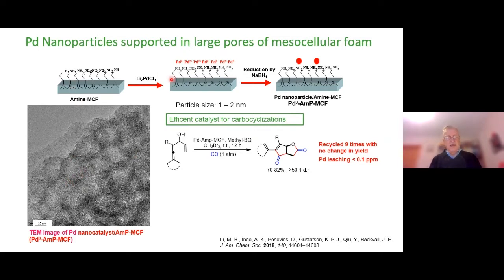And this is what you had on the slide before. You bind this 3-carbon silica with an amine, and you bind palladium 2 and you reduce it. And these nanoparticles are efficient catalysts for carbocyclization. In this case, we use this enallenol, and you use a double carbonylation, so you have 2 carbon monoxide being included in the product, and you get these interesting lactones.